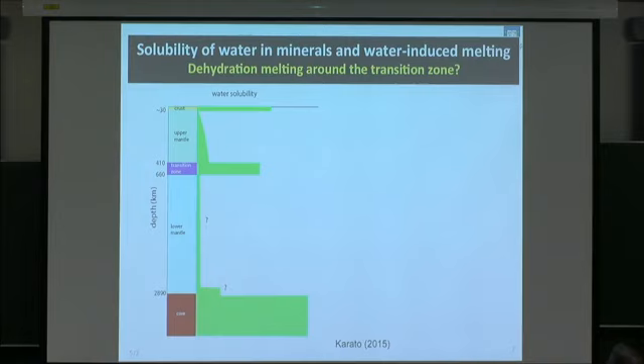The fundamental reason for water enhanced melting is that water prefers to go to the liquid, and only a small amount of water goes to the mineral. Because a large amount of water goes to the liquid, the liquid's entropy, the degree of disorder, increases, and then free energy drops. So that's a fundamental reason why water, and some other impurities, enhance melting.